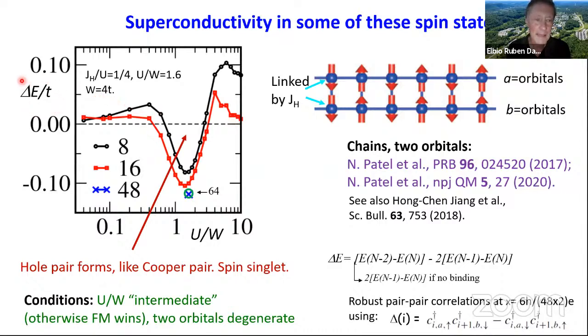So what you have in the vertical axis is a quantity called the binding energy. It is defined here in a bit of a cryptic way. N is the number of electrons of the undoped system. N minus one is when you have one hole. When you have two holes, it's N minus two. So if the two holes were far away from each other, essentially the energy of two holes is the same as two times the energy of one hole. So in the limit when there is no binding of any kind, you will get a result that is supposed to be zero. Here we have only finite size systems.